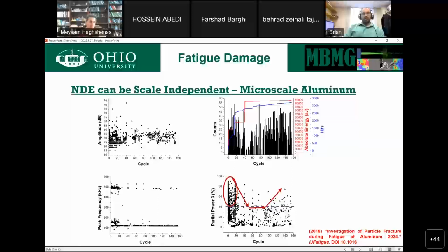And by doing that, we can look at what's happening here and recognize that there is a separation in these features. And by doing that, we can say, well, anything that's in this 500 kilohertz range is probably fracture. And not only that, but we can see how that changes over time. In this case, we're seeing a lot of activity early that kind of decays out. So it seems that by doing a very simple analysis like that, you can determine if there's a change in the damage mechanisms, in what's happening inside your material, even if you're not looking at the same spot that's happening.